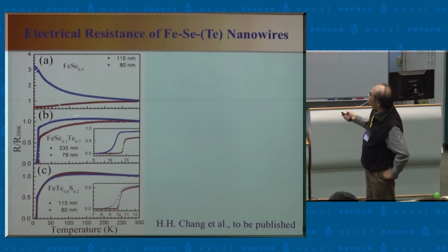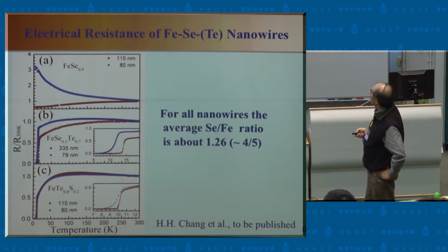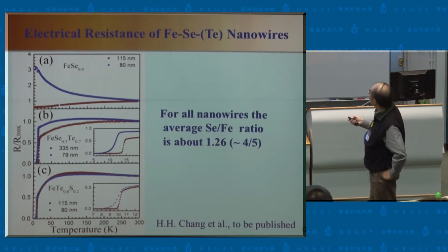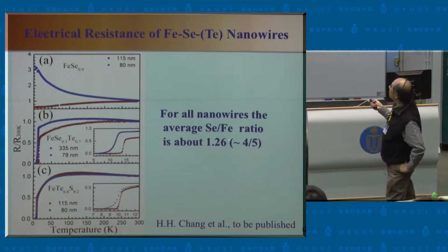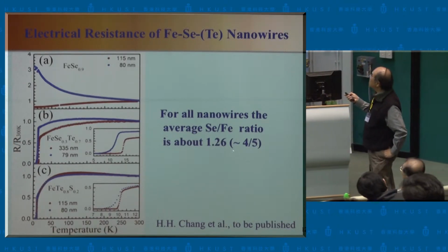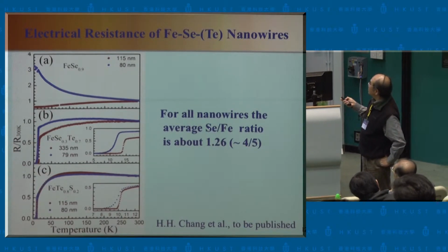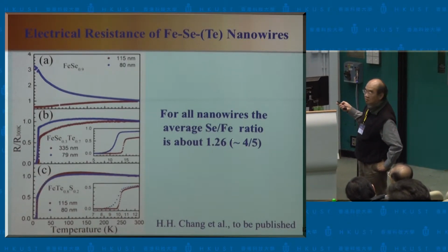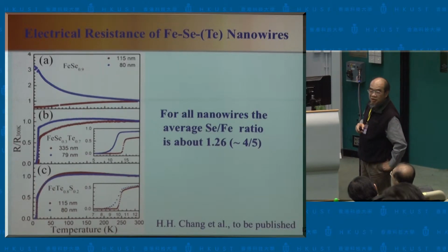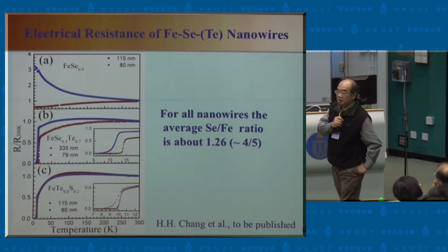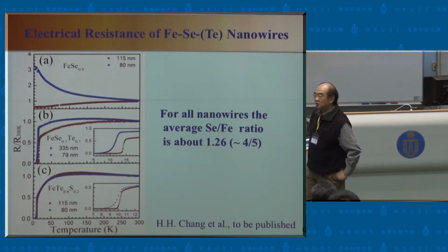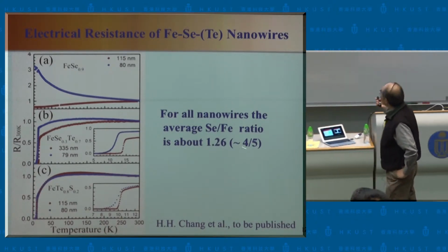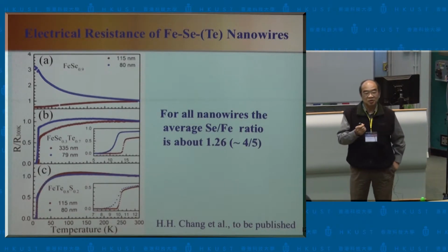This is the high temperature bump, this broad shape of that. But we analyzed the composition in more detail, and we found that actually all the samples have this kind of ratio. The selenium to iron ratio is about 1.26, which is iron deficient in most of the high quality crystals. And this is close to the so-called 4-to-5 ratio.